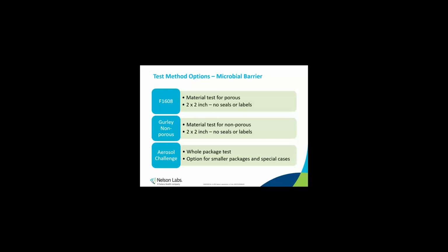The aerosol challenge is a custom test where whole packages are placed in a chamber and lightly showered with Bacillus atrophaeus spores. The packages are aseptically opened and the contents removed and checked for the presence of bacillus using sterility test techniques. As you can imagine, it's not easy to open a package covered with an indicator organism without getting cross-contamination. And the test is dependent on the probability of the organism landing in just the right location to be detected. So there are some limitations to this test. Aerosol challenge is also a pass-fail test.